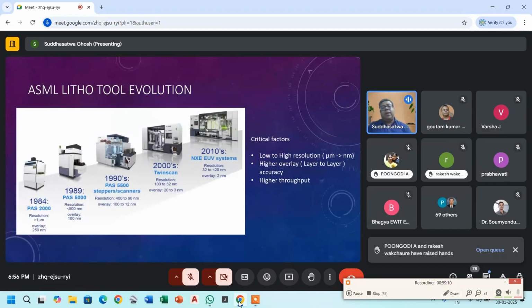This slide is an overview of how the litho tool evolved within ASML. What you see is from 1984, when we made the past systems, the resolution was roughly larger than 1 micron, and over the period the resolution went down, from 1 micron to less than 500 nanometers. Then it comes to 90 nanometers in the 1990s, up to 32 nanometers in the 2000s, and then in 2010 we came with another EUV platform for our machines, where the resolution was less than 20 nanometers.